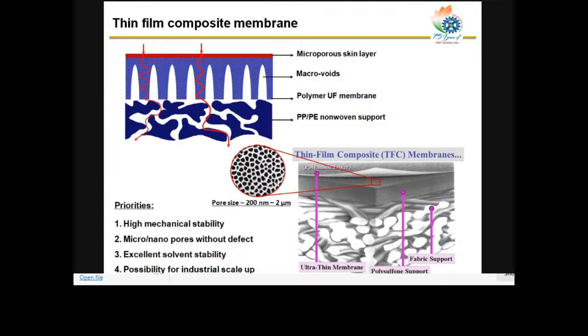So to get this thin film structure, we have to keep in mind that it has to have high mechanical stability, because it needs to work under high pressure, and the top layer should not have any defect. It will also need solvent stability, and it has to have industrial scalability for industrial application.